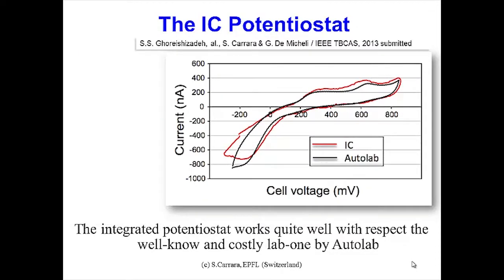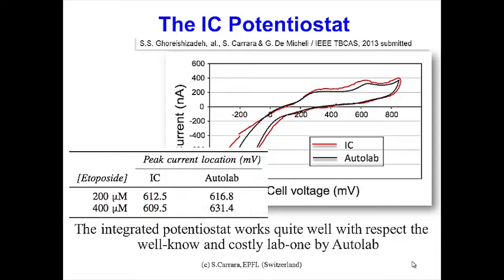We used our developed chip also for measuring drugs, typically for measuring cyclic voltammograms. You can recognize here the peak related to the drugs. We did it up to now with 2 different drugs. This is the case of etoposide, but we obtained similar results with mitoxantrone and other anti-cancer compounds. And once again, we did not obtain exactly the same value, but we obtained similar values for the position of the peak in our cyclic voltammograms.